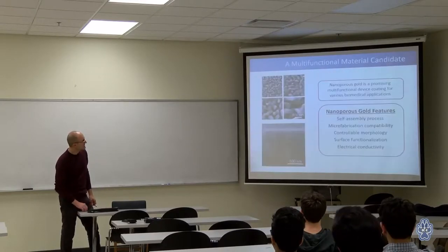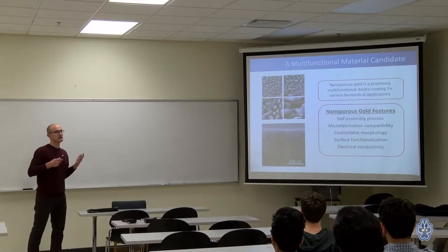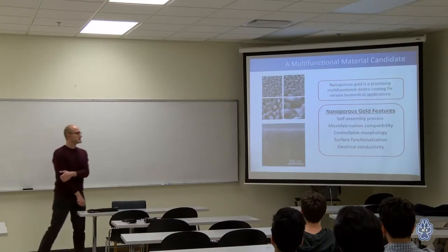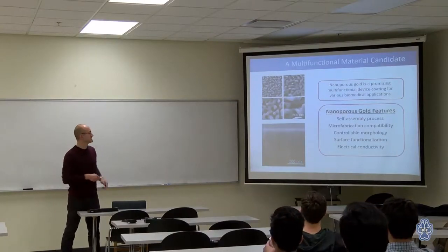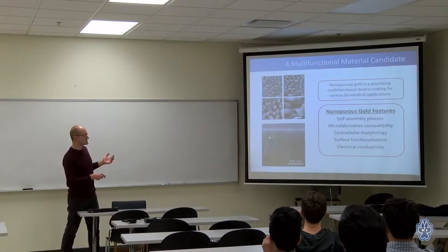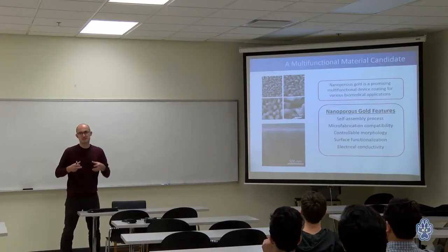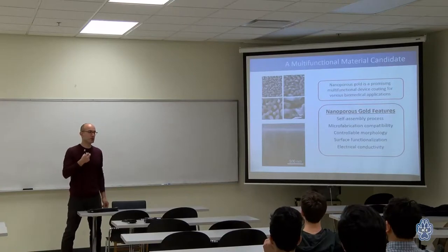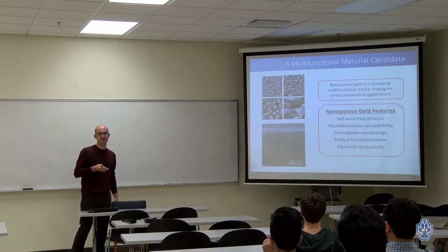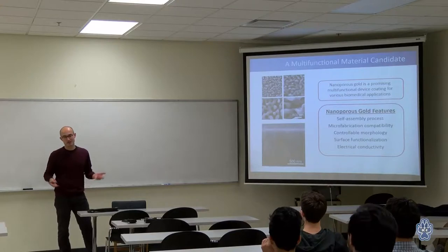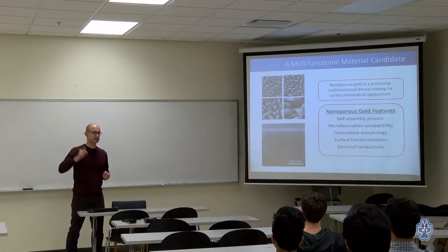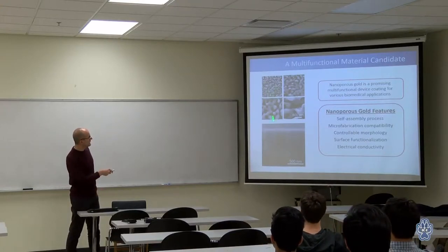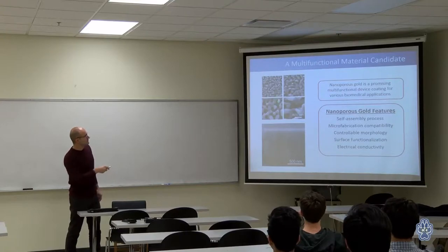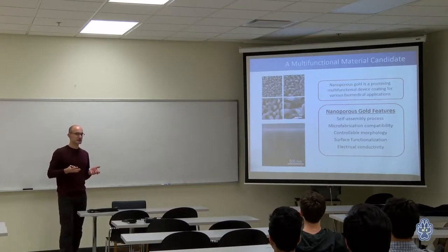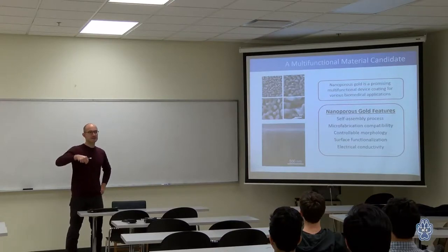Today, what I'll talk about is the material that we focus on in my group. This is nanoporous gold. These are scanning electron microscope images. You can think of this material as just a foam sponge, but the pores are tens of nanometers. Tens of nanometers is about a thousandth of the thickness of hair, so these are very small pores. And this is a cross-section of that. The way we make this is you start with a gold-silver alloy, so it's the white gold that you may have heard of. You dip it in nitric acid.